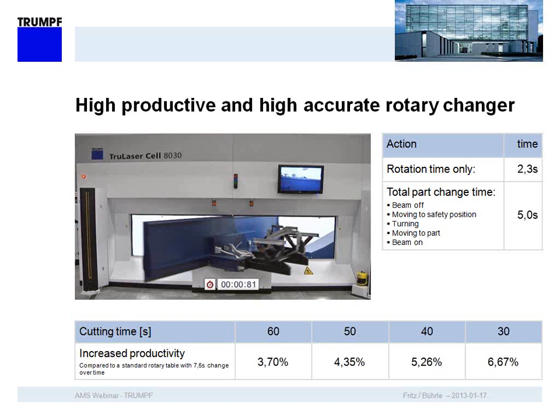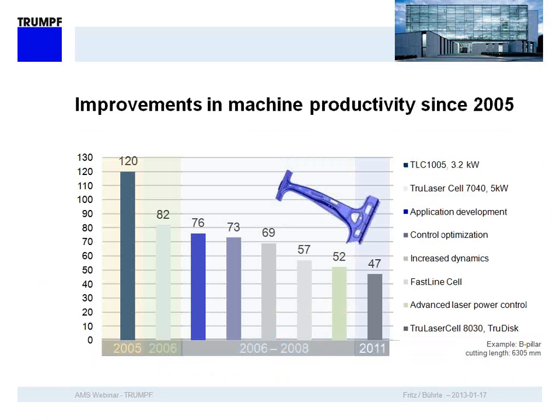Another important feature to increase the productivity, mentioned in the presentation, in the movie, is the rotation time of our table and the total part changeover time. Now if you put this into relation to typical cycle times that you see in those hot stamping components, which is down below in this chart here, typical times range maybe from 30 to 60 seconds. You can see the advantage in productivity just by increasing this rotation time from 7.5 seconds to 5 seconds. The benchmark of 7.5 is because these are typically available rotary tables that we find in the industry, and also previous generations of our machines had this 7.5 seconds changeover time. And we really wanted to set the benchmark, so we have looked into a lot of details of the machine to improve it and to make it more productive.